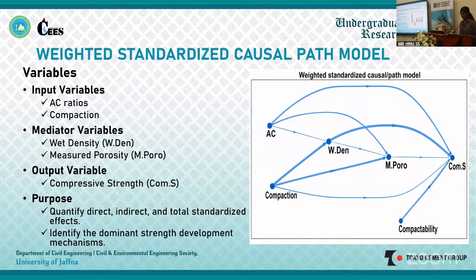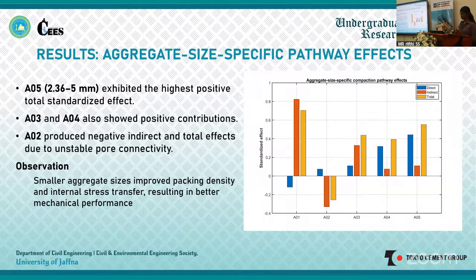The results indicate that the A05, ranging from 2.36 to 5 millimeter, exhibits the highest positive total effect. Also, the A03 and A04 showed the positive contribution, but A02 produced the negative effect and the total effect due to the unstable pore connectivity. These findings indicate that the small aggregate size improves the packing density and the internal stress transfer. It results in better mechanical performance.